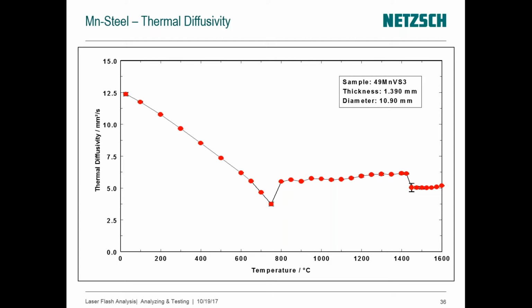In that case, we are showing that as you heat up steel, you go through the phase change around 700 some degrees, you see it, and when the sample melts at above 1400 degrees Celsius, you can see that too. So being able to monitor the thermal diffusivity as you go through those events is very interesting.